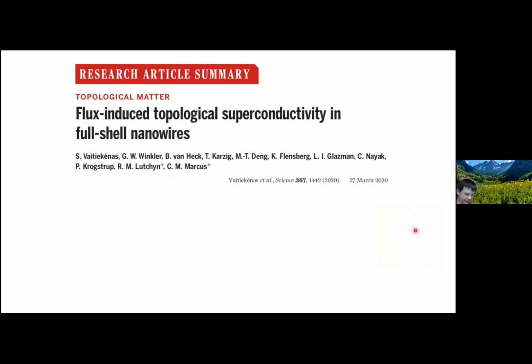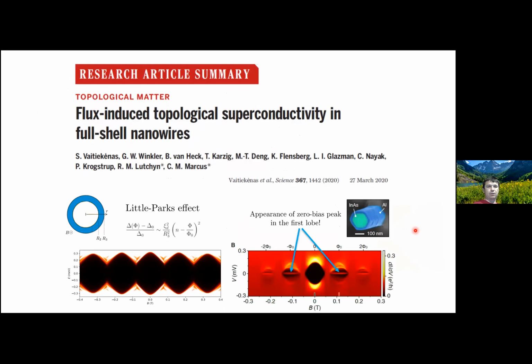Yeah, so let me switch gears and talk about flux-induced topological superconductivity in full shell wires. This is a new idea for how to realize topological superconductivity, again in a similar semiconductor-superconductor heterostructure, but the control parameter here is the flux. A very interesting phenomenon was observed by the Copenhagen group led by Charlie Marcus: if you take a semiconductor wire and create this superconducting shell and look at the local density of states in the wire, it behaves very differently than the well-known Little-Parks effect, where we just have a simple superconducting cylinder with a hole inside, or an insulating core.